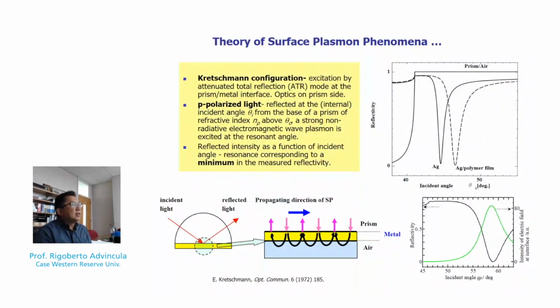Now, what this translates to, and this is really the more important aspect because of our limited time, is that surface plasmon can be utilized to investigate the dielectric properties of a thin film. So thin film, meaning you have a dielectric media of as little as 1 nanometer or less, or if you have a dielectric media in the order of microns, one can, of course, use waveguiding to investigate the properties. But assuming you have a thickness of about 100 nanometers, as you excite the light using what they call a Kretschmann configuration, a type of ATR mode, as I showed earlier, where the light comes through a prism with a metal layer, that will result in a dip in the reflectivity curve.